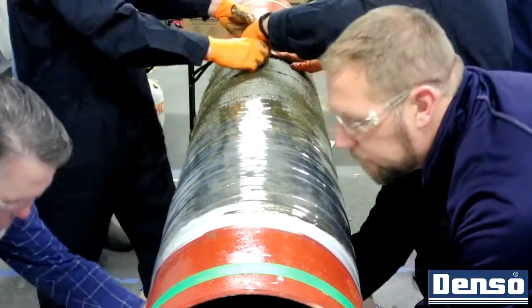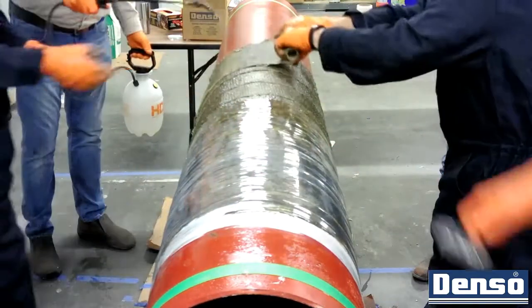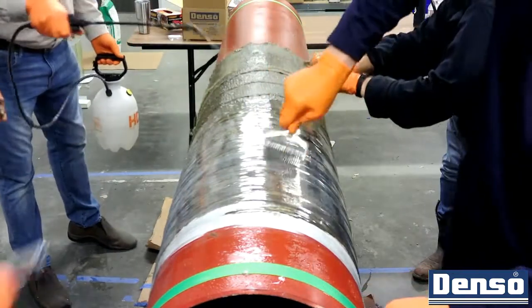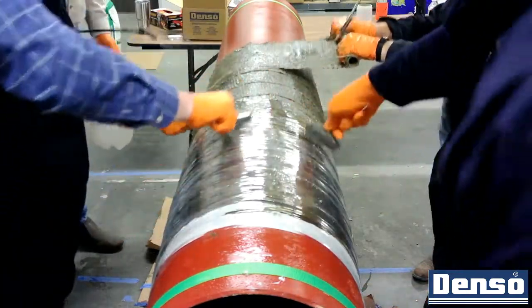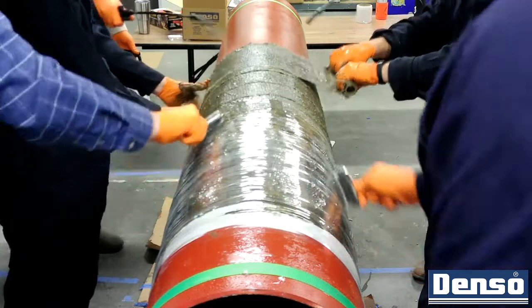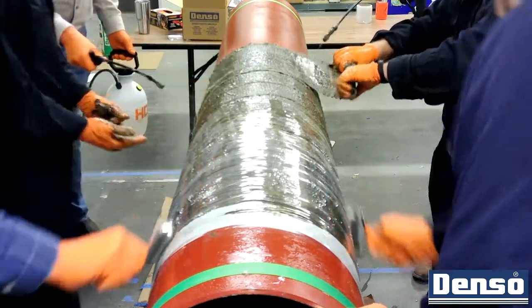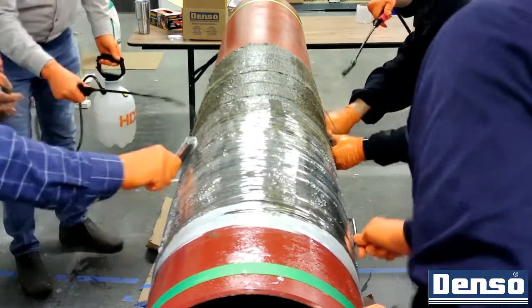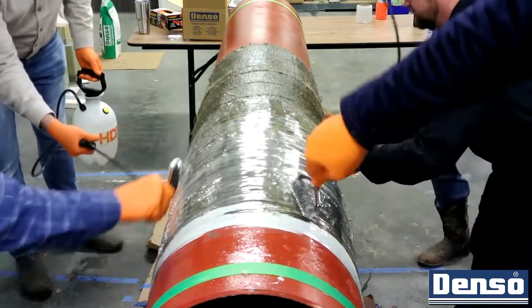Once fully compressed, use the Denso perforating tool to puncture the Polywrap. This will allow for excess resin, moisture, and CO2 from the reaction to escape. Perforate using enough pressure to get through the Denso Polywrap, but not through the layers of bore wrap.